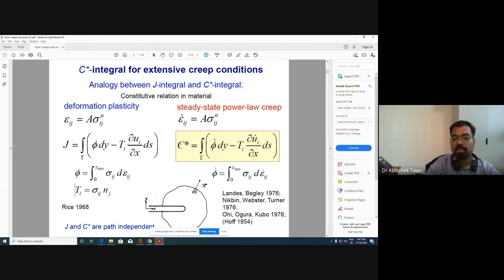So this is the displacement gradient in the x direction. And ds is the amount on the contour which you are taking. Along that contour, you are calculating this property. This symbol with the contour gamma indicates that. So this equation, as we have discussed before, says that the amount of energy which is dissipated must be equal to the amount of energy which is supplied. So this is simply the conservation of energy formula. Here we are doing something per unit volume, per unit area, per unit crack length. So strain energy density is per unit volume, and traction into displacement gradient into ds also gives you an energy value, and then the remaining of that becomes the J integral, which is the singularity. So this part we have discussed, and there should not be any confusion in this. The idea was given by Rice, James Rice, so that's how J comes.